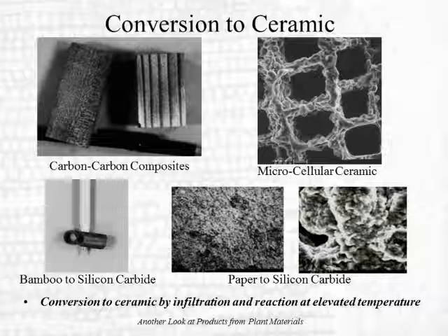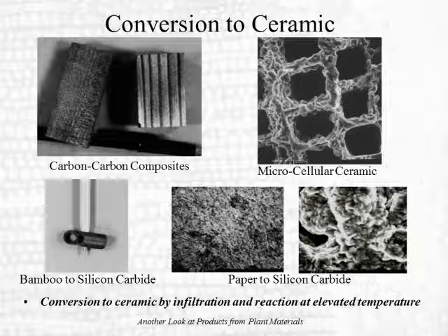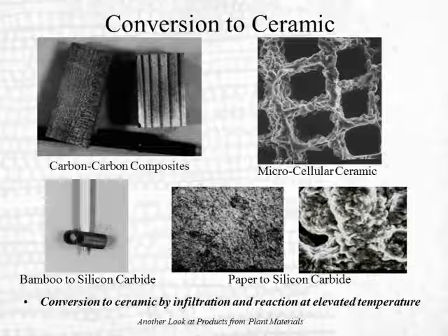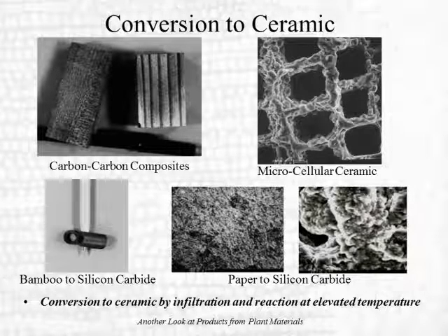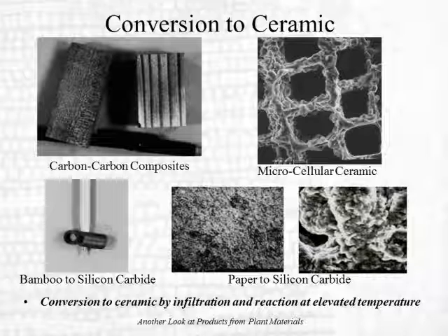Conversion to ceramic. This was a piece of redwood. All what used to be cellulose and lignin of the cell walls was converted into charcoal, converted into carbon, and then that converted into silicon carbide. And that picture is there because it's so beautiful. It shows all these silicon carbide crystals. And it retains that cellular microstructure that the wood originally had.